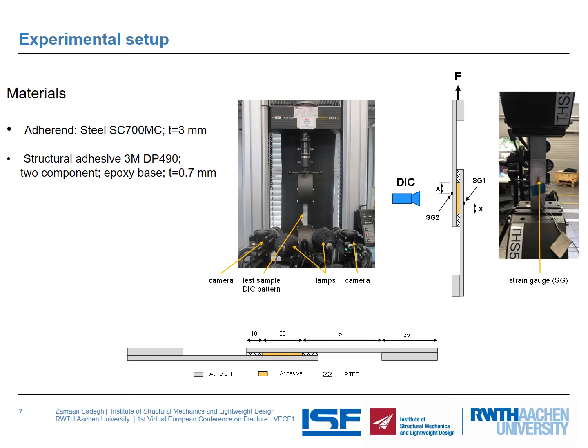The tensile test was monitored with a DIC system in order to record the local deformation of the joint over the tensile test. Also, for every individual test carried out in the present work, two strain gauges were mounted, one on each side of the single lap joint, and the location of the strain gauges was determined with the help of FE analysis, which is exactly the same point that we previously discussed, the point with zero strain value.